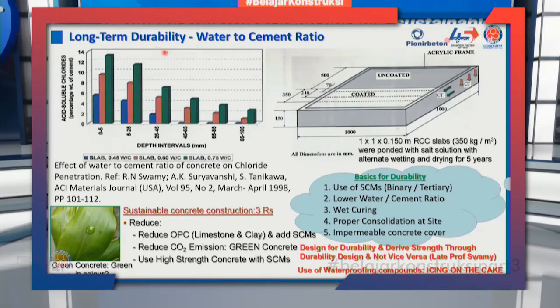You can see here, we cast big slabs, 1 meter by 1 meter. This research was done in Sheffield when I was working in Sheffield. The thickness of the slab was almost 150 millimeters. The bars were in the lower part. One part was coated, the other part was not coated. We exposed both parts to chlorides for 5 years. It's a long-term study. 3 days wetting with the salt solution and 3 days drying. So it went for 5 years.